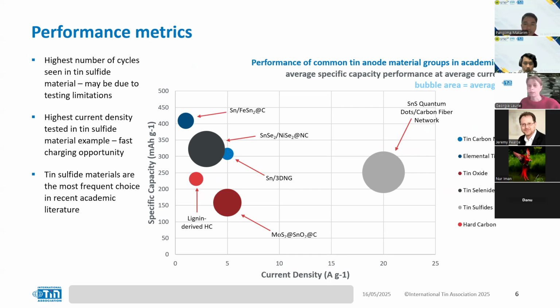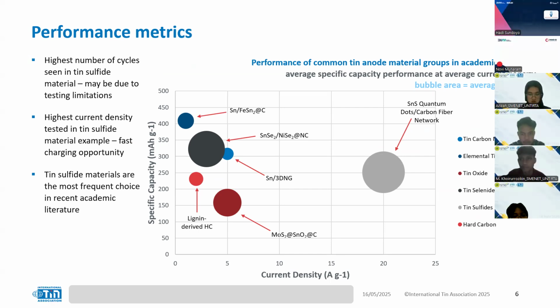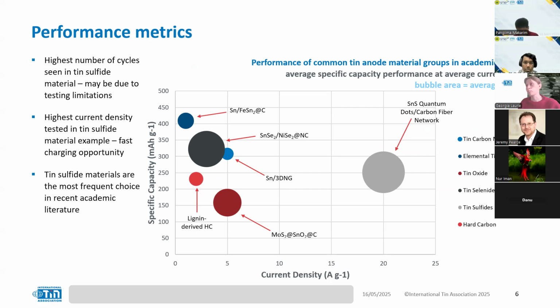So the graph that you can see on the screen highlights the relationship between specific capacity at varying current densities, and then also an additional layer of information is the size of each bubble. So the size of each bubble represents the number of tested cycles for each material in the literature. But it's important to note actually that some of the materials testing at an academic level could be limited by time and equipment availability. So if we have a look at some of the results on the graph, tin sulfides appear to be a very promising option.